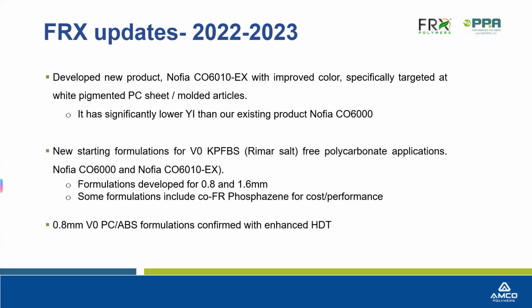We also have starting formulations for replacement of the fluorinated salts that have been used in polycarbonate. They're called Rimar. We're very excited about this because of the recent announcements of moving away from PFAS as rapidly as possible. Here, CO 6000 and Nofia CO 6010EX have been demonstrated in formulations for 0.8 and 1.6 millimeter V0 applications. In some cases, we include a co-FR phosphazene to help balance cost and performance. In our PC blend applications, specifically PC/ABS, we've been able to demonstrate an enhanced heat distortion temperature by as much as 30 degrees C, and we are V0 down to 0.8 millimeters.